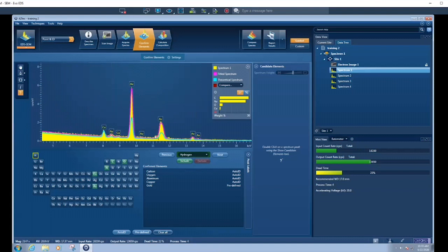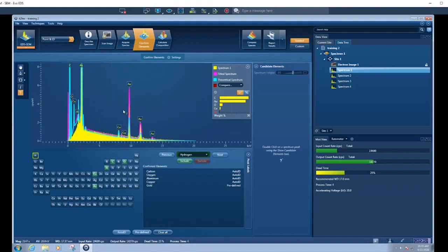So this is where we might have to start to take into consideration that this is not a very accurate fit, and that's probably because this is a thin film. When it's doing all of these calculations, it's assuming a bulk specimen, and we're working on a thin film. So whenever you guys are working with very small particles or rough surfaces and things, that's where you can't take the accuracy of these values. You have to take into consideration other effects.